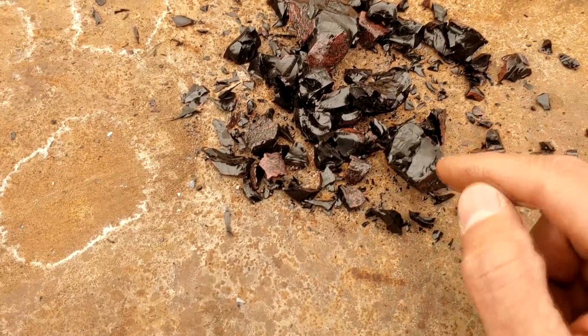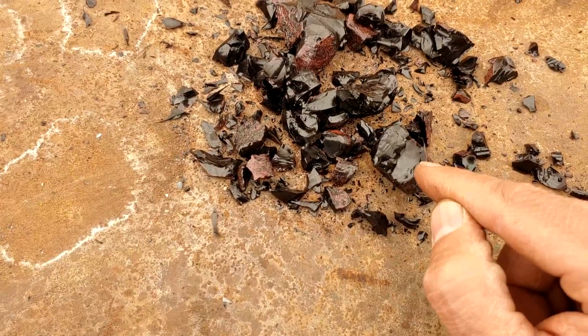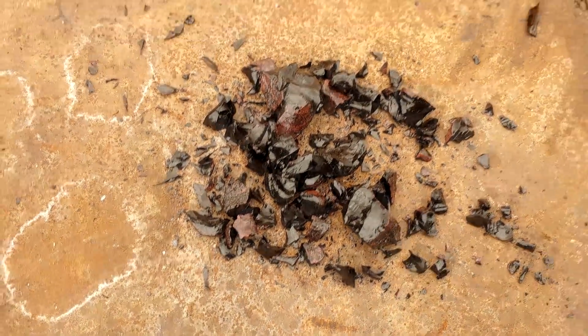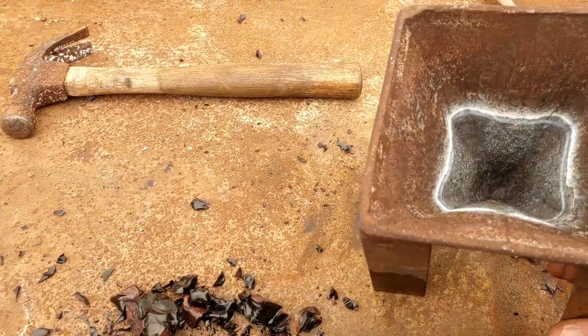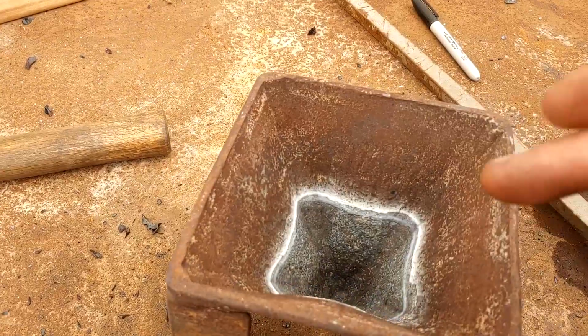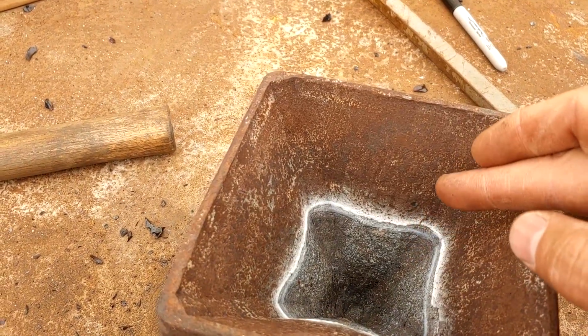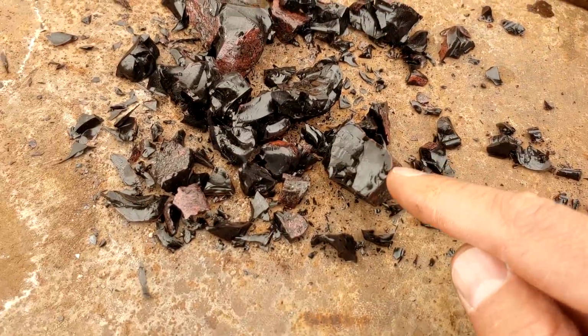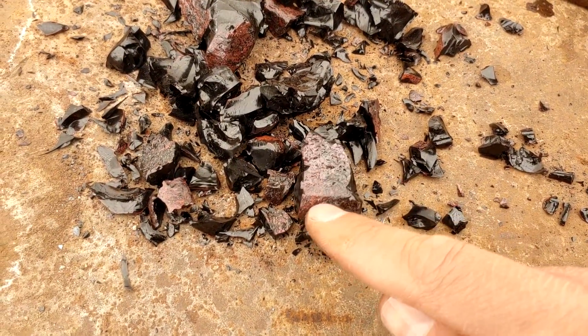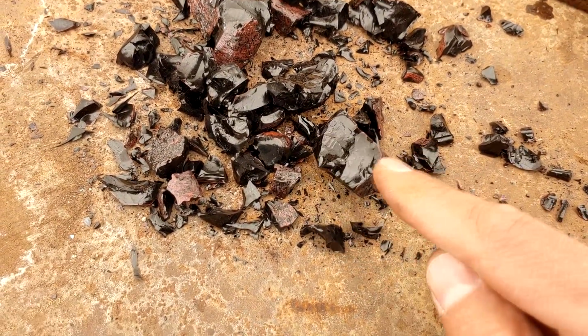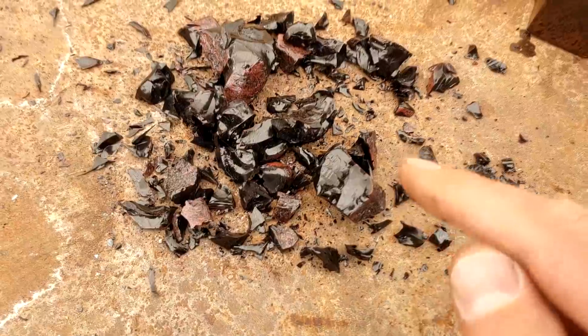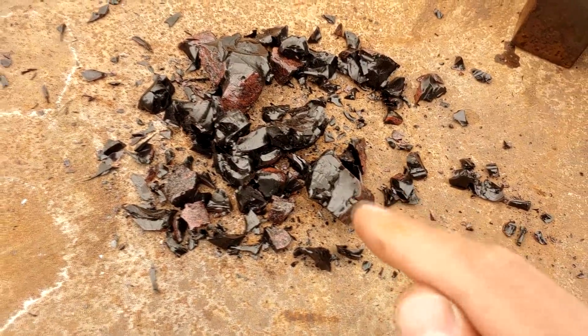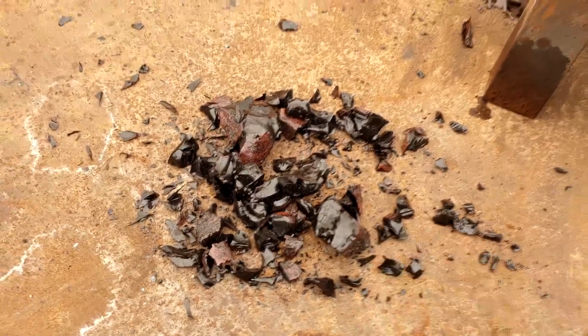And I've had comments in the past that people think that when I pour that hot slag into the cold cone mold, the copper in the slag reacts with the iron and forms this little skin of red copper that comes out of the slag solution. So is that what's happening? Because I don't have any metal button at all.